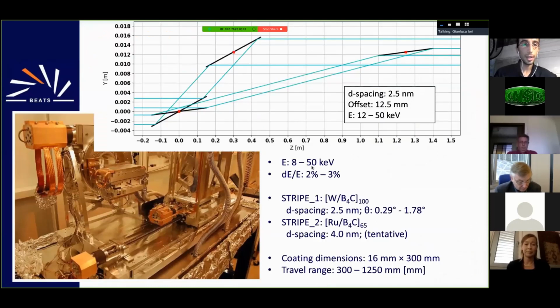We have actually simulated the working regime of this device for the angles and energies that we need. We will have 8 to 50 kiloelectron volts covered by these multilayers, with a rather broad energy bandwidth between 2 and 3%. There are 2 different stripes, one with a tungsten coating and the other with ruthenium, and different d-spacings as well, to optimize the work at high energy with tungsten and at low energies with a ruthenium coating. The travel range can be around 0.3 to 1.25 meters. With these parameters, we will cover the entire energy range that we need for our application.